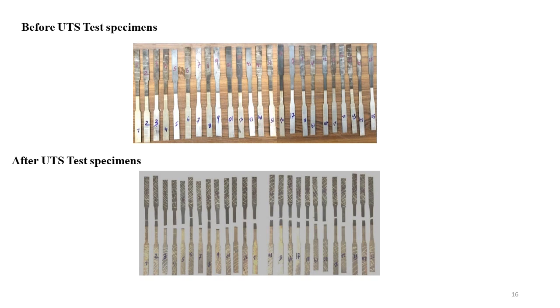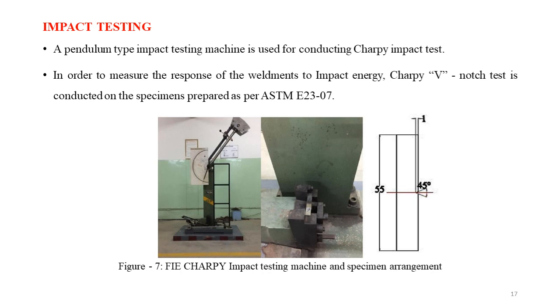As per ASTM E8, the dimensions are considered, and the UTM, the universal testing machine, is used. These are the UTM specimens, prepared by EDM. After the UTS test, these are the specimens, and in the majority of the work the specimens fail away from the weld joint. Then an impact test is conducted, a Charpy impact test, and the specimen is prepared as per ASTM E23. These are the specimens of the impact test and the tested specimens.